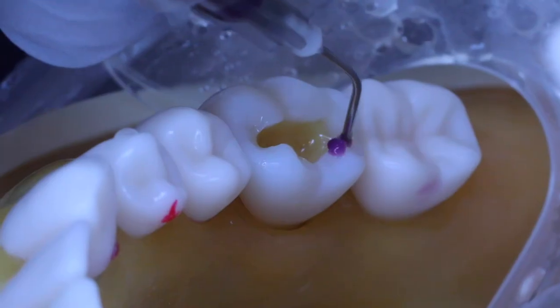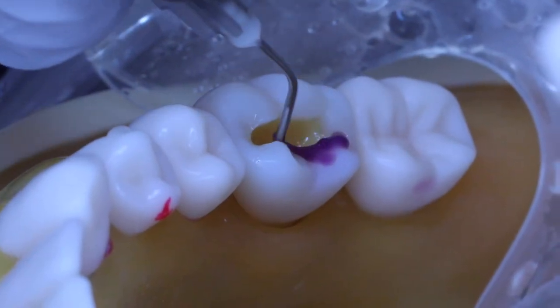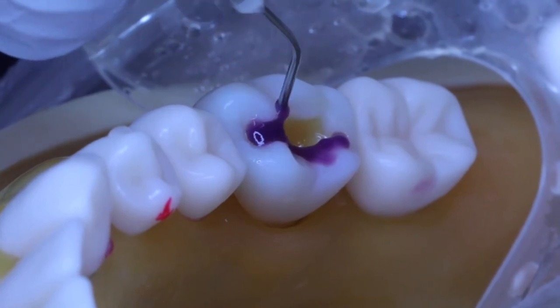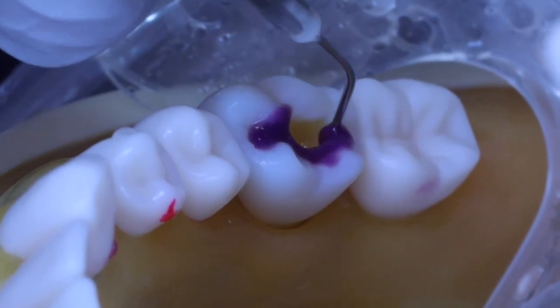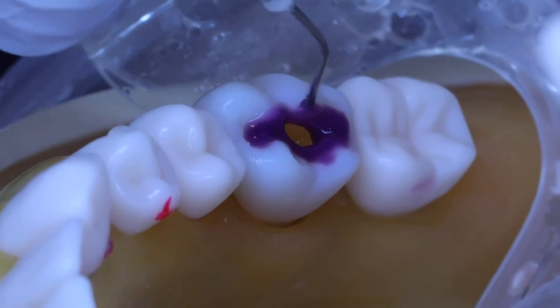All right, so the last really big update I want to give you on Universal Adhesives is related to when you use these in a selective etch mode. Now, personally, I prefer to do either a total etch or a selective etch when using Universal Adhesives. Studies show that if you etch enamel with phosphoric acid, you're going to get a better bond to the enamel. Studies also show that if the actual universal adhesive contains 10MDP, a self-etch mode to the dentin is actually really good and it's very strong.